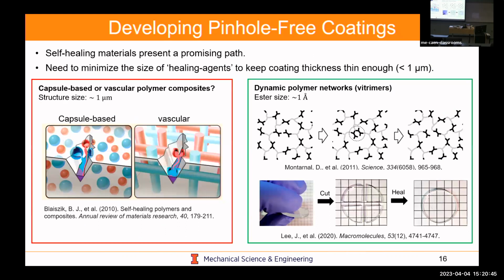So we said, if pinholes are the source of the blisters, can we get rid of pinholes and therefore prevent blisters from growing? And so one promising path that we looked at was self-healing materials. These are not new and not developed by us. People have looked at capsule-based materials and vascular materials where essentially once you rupture the material via some defect, it'll release a payload, typically an epoxy or an epoxy resin that will then cure, and then your pinhole will go away. And people have looked at this at Illinois and other places.